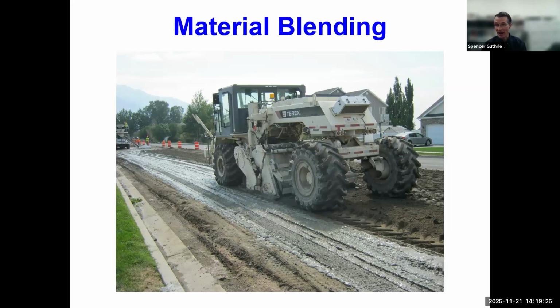Generally speaking, unless we've added a hydration stabilizer, as I mentioned earlier, we try to get the cement incorporated, mixed in to that pulverized material, normally within 2 hours. We need to do that quickly because otherwise the cement will begin setting, and then we will not achieve the proper compaction and grading that we want.